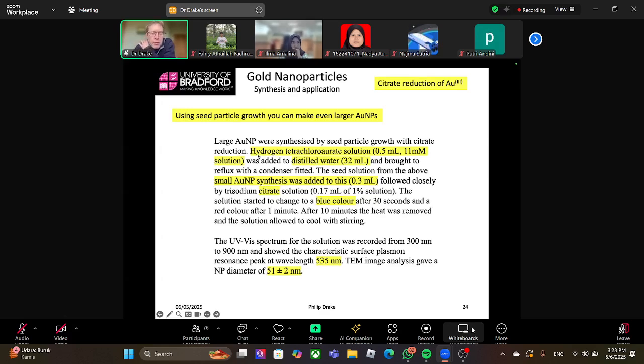In seed particle growth, you take your gold chloroaurate and mix it with some pre-made gold nanoparticles of a known size. You then add in the sodium citrate, and you start to get growth on those particles again, which gives you a blue color after about 30 seconds. And now the SPR peak has shifted. It's gone from 517 to about 535. So I now know that these particles are about 51 nanometers. So the SPR peak is the way to record the nanoparticle size.